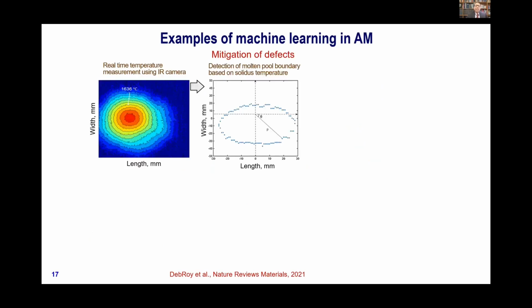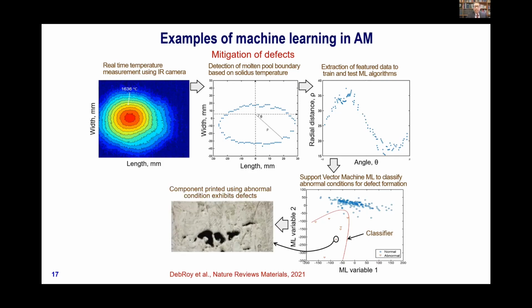So examples of machine learning, there are many, and you will find many other examples in our Nature Reviews paper published last year. Like here, this is the result of a thermocamera experiment. This is the trace of the solidus line of this alloy. And if we plot it as a function of this angle theta, we get a feature like this. And if we separate that feature using support vector machine, we can have it classified into safe region and not so safe region. And we can take a sample to see that unsafe regions do have defects.